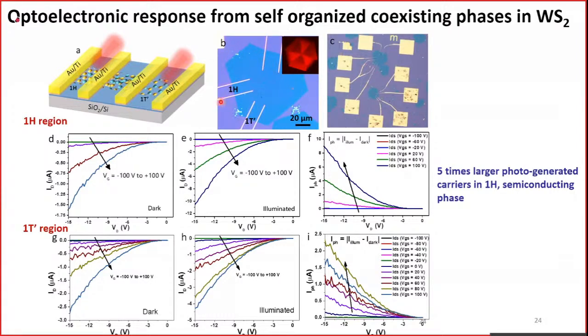Again, by electron beam lithography, we make a device. We know this particular facet is the 1H phase. The smaller facet is 1T. So by looking at both the optical imaging and the fluorescence imaging, we identify that. Then we try to see how the current changes when you shine a light. What we found was that compared to the 1T prime, the 1H phase shows 5 times larger photocurrent.